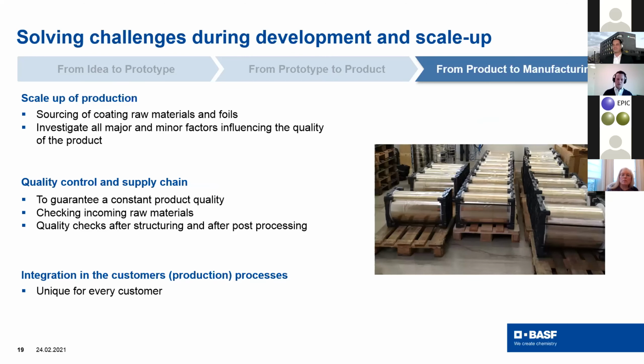You want to make tens of kilometers of this stuff. So you need to source the materials, the raw coating materials. Instead of kilos, 10 kilos, you have 100 kilos or 1,000 kilos. For the foil, you also want to investigate the smaller defects which happen in 1 or 2% of the cases. You implement a quality control, especially for this product. You're talking about a glare control foil, which of course has special color requirements. So then you, for example, implement extra color measurements for your raw material inspection. And then you integrate it at the customer, which is unique for every customer.